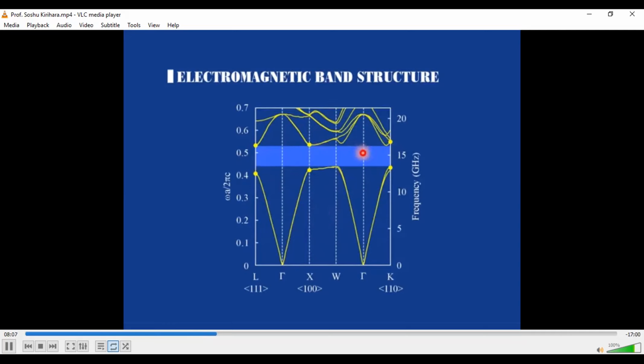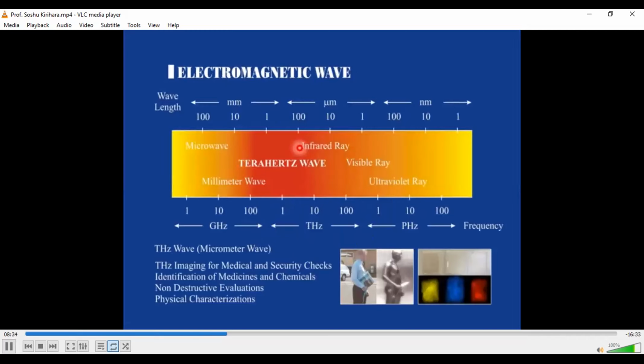The solid circles show the higher edge and the lower edge of the measured photonic band gap. You can see the calculated result and the measurement result have good agreement. Anyway, we want to try to control the higher frequency electromagnetic wave, especially the terahertz wave, the micrometer order wavelength electromagnetic wave.